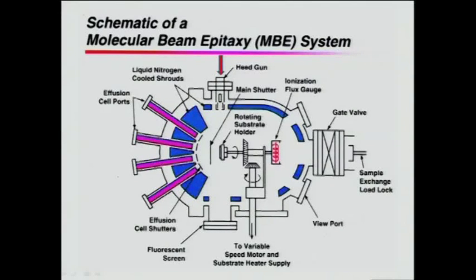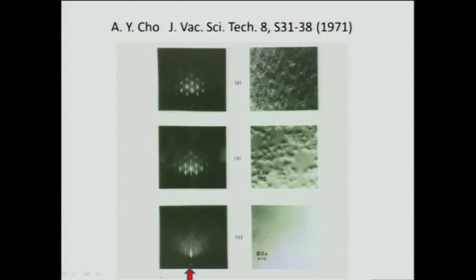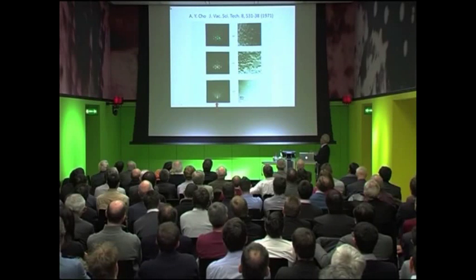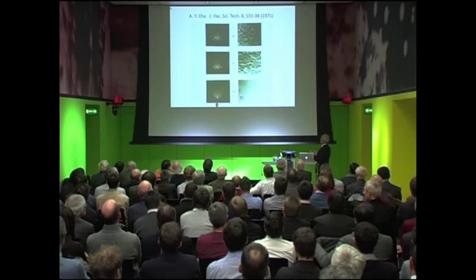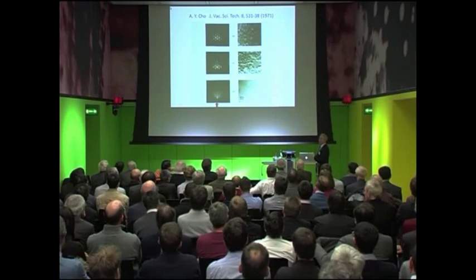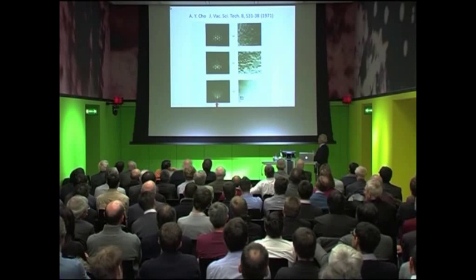So what we see in this diffraction pattern is shown here. On the left-hand side, these are the diffraction patterns. On the right-hand side is the corresponding surface, looking at this electron micrograph, how the surface looked. I wanted to show you here at the beginning, before desorption of the oxide from the surface, there is amorphous oxide on there. After desorbing the amorphous oxide, we see spot diffractions. And that surface is matted after chemical etching and heating, forming a microfaceted surface.